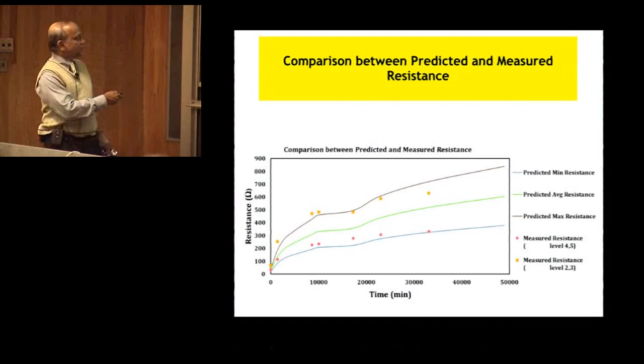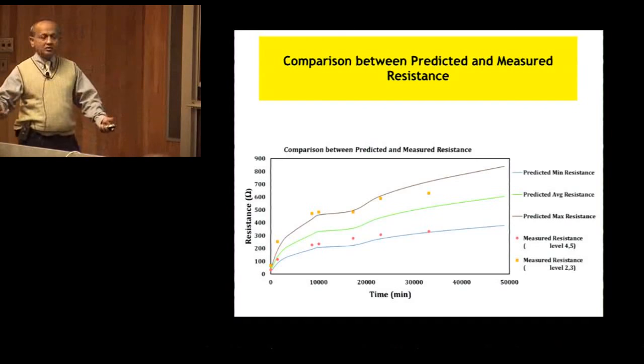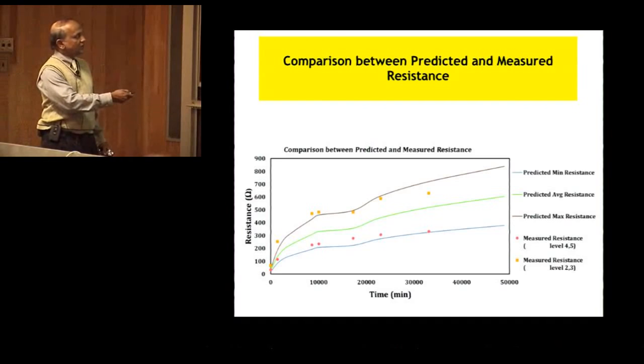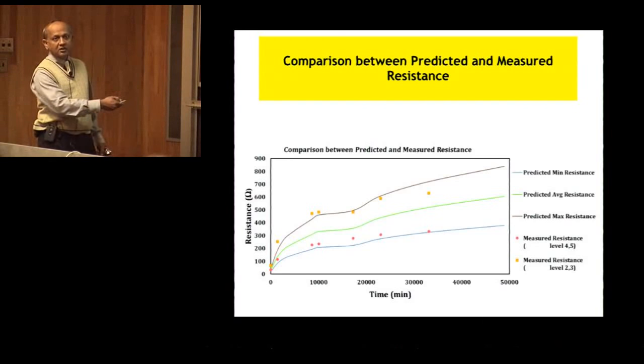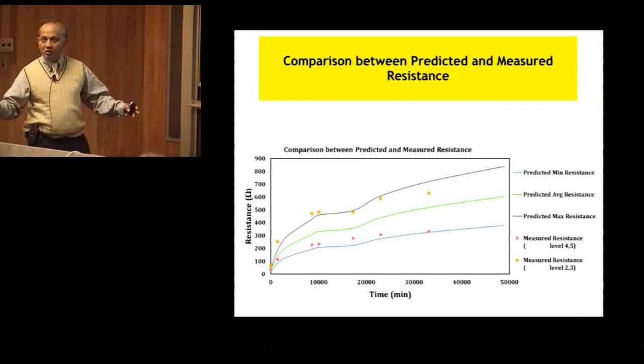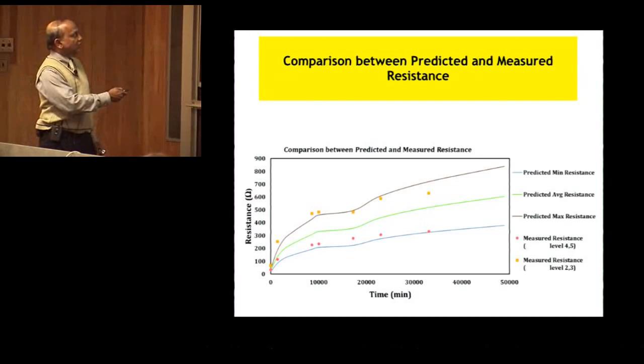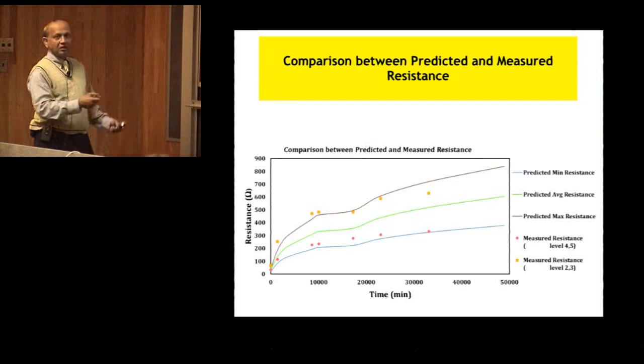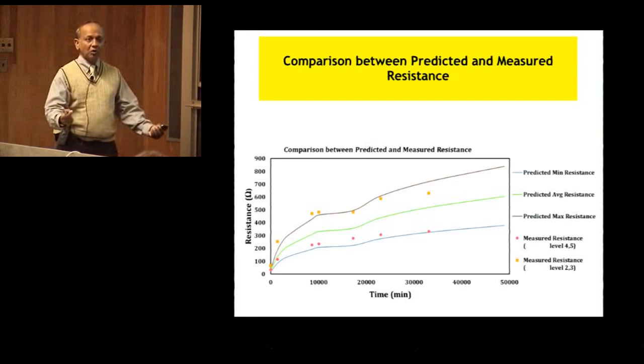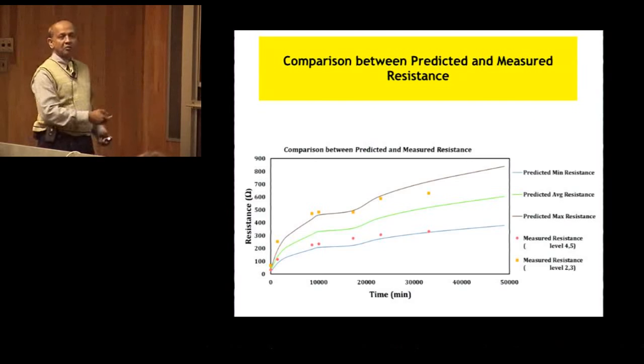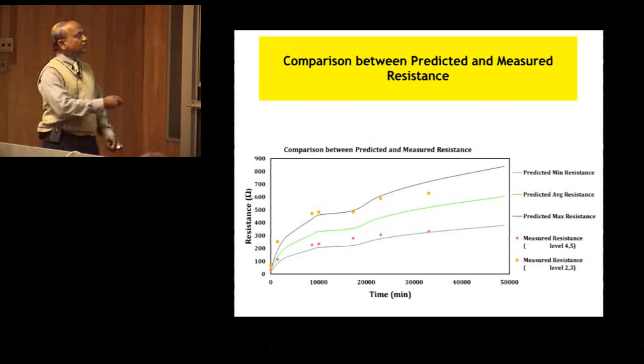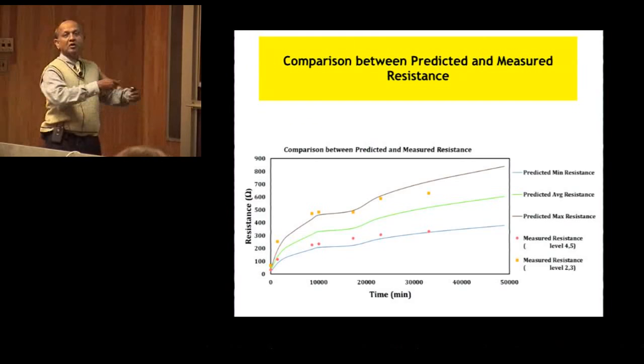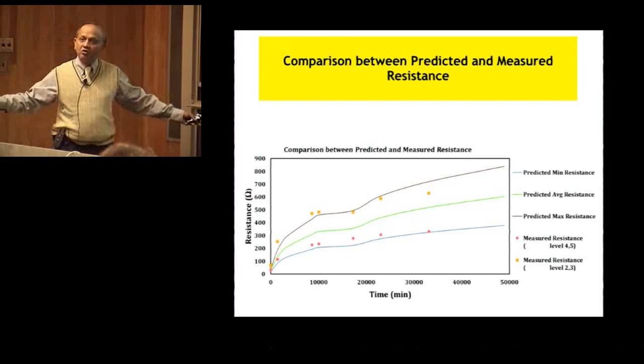Now, this study is a continuing study in the models. This study is over 30 days now. We have done it for 30 days. Cement is hydrating in the models. And these points are the experimental points that we are measuring in the models, and we have come up with models to predict it. So we can predict this for a very long time. We have the models to predict it.